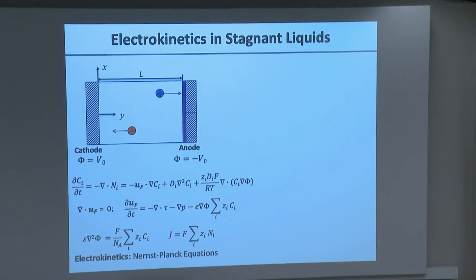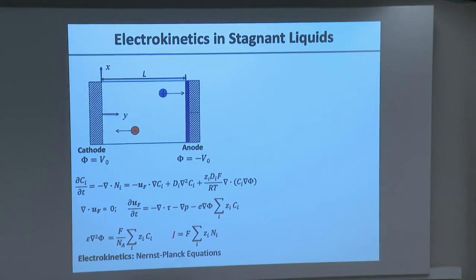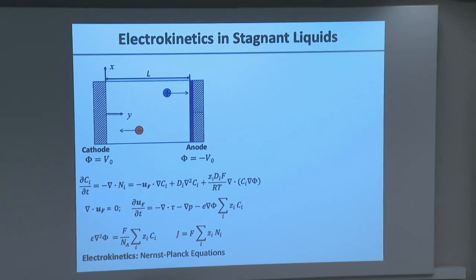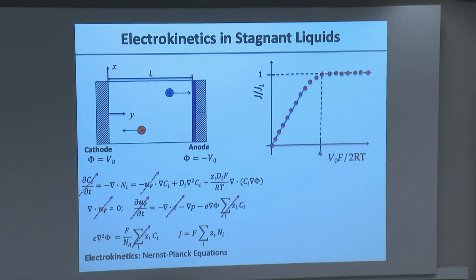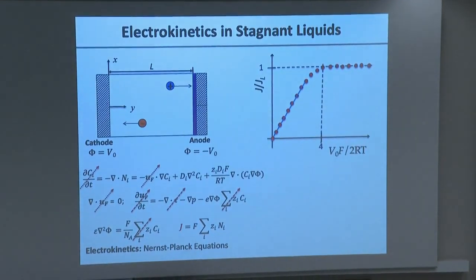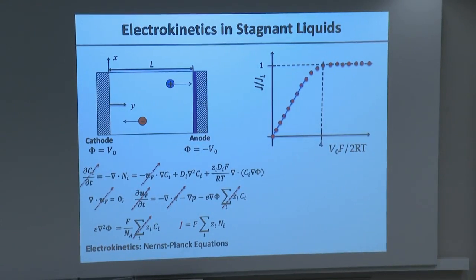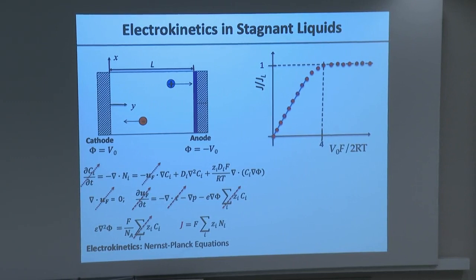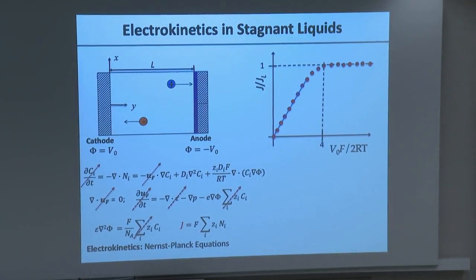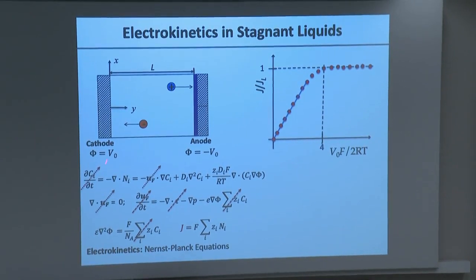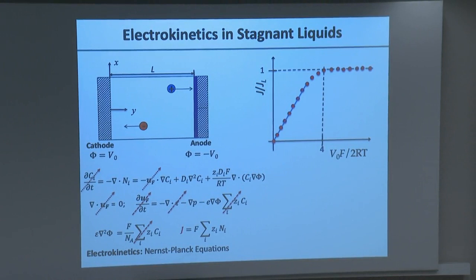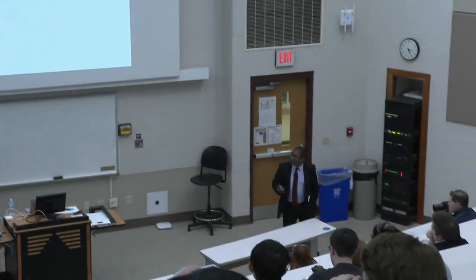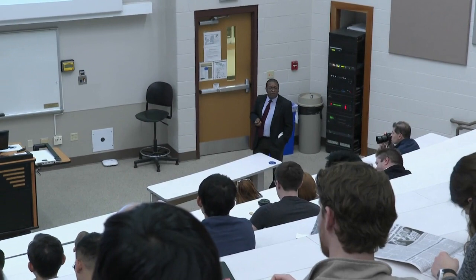Now, in principle, these equations are a set of very complicated coupled differential equations that could also be time-dependent, that you have to solve to determine the concentration of ions and how ions move, the velocity in the electrochemical cell. Now, people are lazy, and with some justification in general, and they say, well, it's a battery, it's a closed cell, so we don't expect any fluid flow to occur, so we set u_f to be zero. We say, oh, we're going to wait long enough, and we're going to consider this problem to reach steady state, so we set the time-dependent terms to be zero. And we say, well, electroneutrality is typically right in liquids, so we're going to set the right-hand side of the Poisson equation to also be zero.